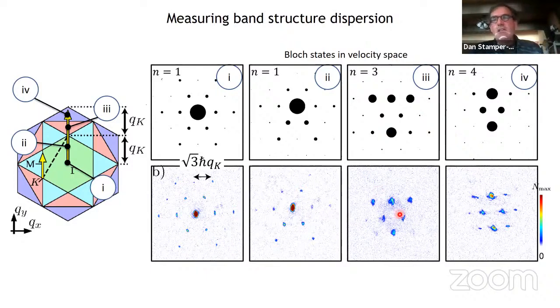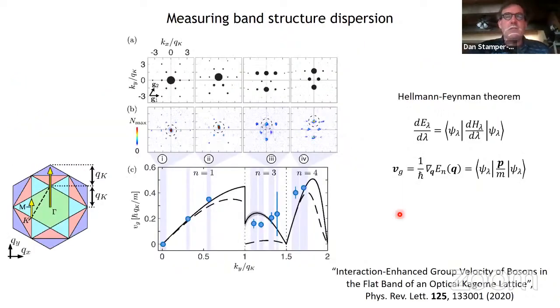But let's try to look at these data a little bit more carefully and make a quantitative statement. In particular, we're going to use this relation over here, which is robust. It tells us that a quantity known as the group velocity, which can be defined as the gradient of energy versus momentum in the band structure, is identical to the average velocity of the Bloch state. Very simple relation. And here's the momentum distribution, so we can just take the average velocity from this distribution, and we measure the group velocity directly. Here's the group velocity at various locations in the first band, in the third band, and in the 4th band.